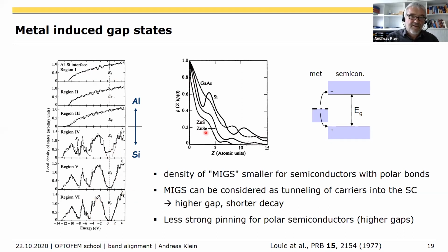And in principle, what they could also show is that these induced gap states decay from the interface faster if you go to more ionic material. So this is for silicon, that's for gallium arsenide. Zinc sulfide, zinc selenide are more ionic. They decay faster, and they simply decay faster because the band gap of this material is higher. And if we consider this as tunneling, and this as our tunneling barrier, if you make the band gap larger, your barrier will increase and the decay of the wave function will be faster. This is very simple, again, quantum mechanical tunneling. So you can understand this dependency. Larger band gap, less induced gap states. That's an important thing.